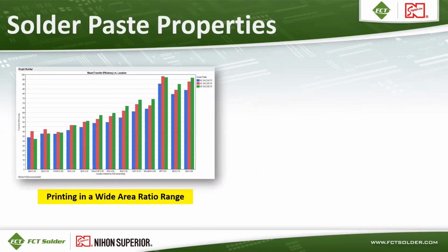First of all, it would be important to have the solder paste be able to print in a wide area ratio range. This is data from an older paper that we wrote on a no-clean solder paste using SAC 305 type 3 and type 4 and type 5 powders. The area ratio range shown here is 0.30 all the way to 0.80. And so we're pushing solder paste well beyond the normal IPC standard of 0.66 area ratio.